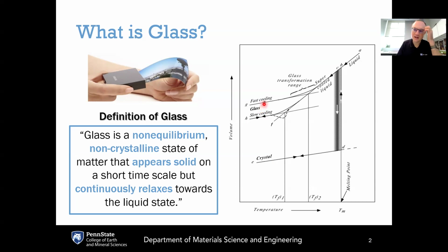Now, it's not enough to just have the chemistry of the glass, the temperature, and the pressure. That's not enough information to be able to define the state of the glass. That means we need to introduce another thermodynamic parameter. The easiest, simplest thermodynamic parameter to introduce is what's called the fictive temperature, labeled as TF, T subscript F, as shown here.